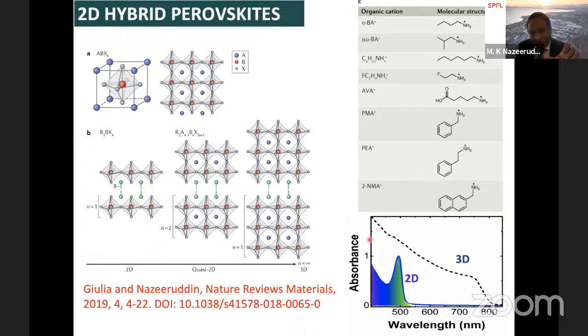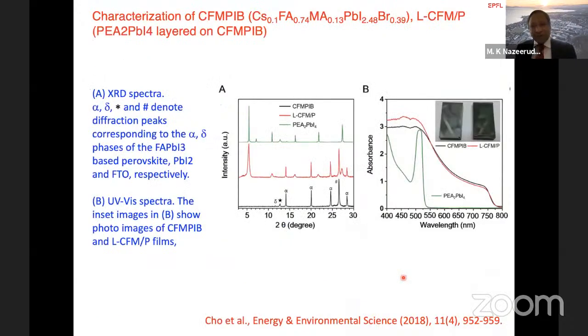The drawback of this three-dimensional perovskite is the stability, and stability is not very good. So what we have to do is we change the dimensionality and we go for the two-dimensional materials using some of these cations shown highlighted here. But you can immediately find out that the two-dimensional perovskite absorbs only a small portion of the visible light. Thereby, the efficiency of these two-dimensional perovskite materials can be significantly lower. Think of combining three-dimensional perovskite, which absorbs all the visible light, with the two-dimensional perovskite, which is not absorbing, but which is providing enhanced stability. That's what you will see in my next slide.